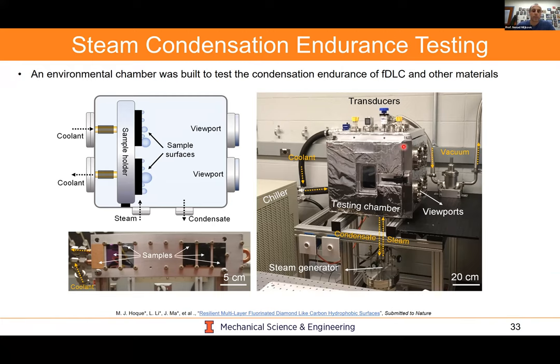It's a vacuum compatible chamber that we could mount samples to. These are samples in the bottom left here that we mount, and we could observe dropwise condensation and how it changes over time. And so we put, whether it's smooth copper, just as a reference, as a control sample, HTMS, Teflon, C4F8. And then on the right here, you're seeing these diamond-like carbon coatings, which have been in there for multiple years.